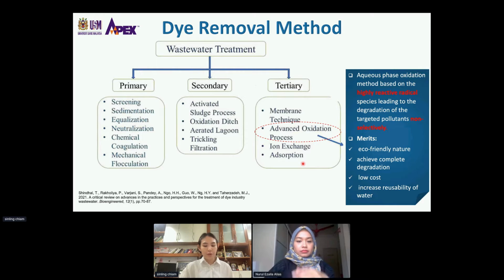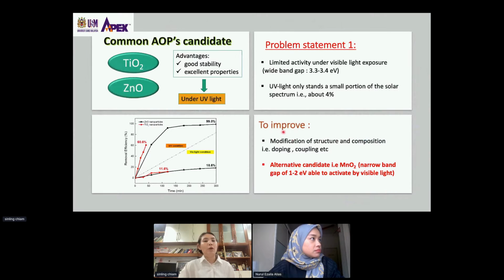Among them, advanced oxidation process has been reported as one of the efficient procedures. It is based on highly reactive radical species leading to the degradation of the target pollutant non-selectively. The merits of advanced oxidation process include eco-friendly nature, ability to achieve complete degradation, low cost, and increased reusability of water. The common AOP candidates are titanium oxide and zinc oxide. They show good stability and excellent dye degradation properties under ultraviolet light. However, due to their wide band gap, they have limited activity under visible light exposure.